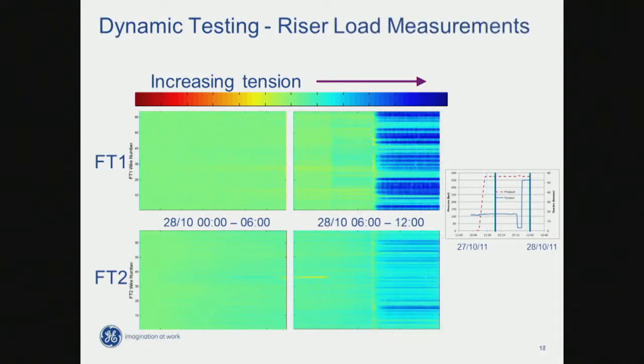Just moving on, this is between these 2 points, so it's constant load, and clearly nothing much happens, as you'd expect, of course. And this is when we just move to the right in the time constant. Again, you've got this constant loading period, this discontinuity in axial load. You can see it if you look carefully, as a witness mark in the trace, and the load starts to pick up. But the wires take time to settle down. There's a time constant to these materials, which certainly isn't allowed in the calculation. But this is all about trying to get underneath the detail of how these materials behave, and maybe there are some thoughts that could go into this in terms of thinking about design and qualification.